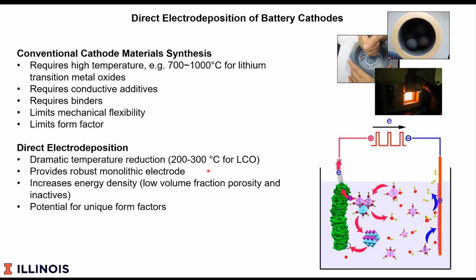The electrodeposition approach contains no additives, and as I'll show you, it forms robust monolithic electrodes. And what we find very importantly is that it allows us to carefully control the crystallography as well as the internal pore morphology. And that's important because the lithium ion and electron transport is very anisotropic. And so by controlling the crystallographic orientation, we're able to orient the material to provide fast kinetics.